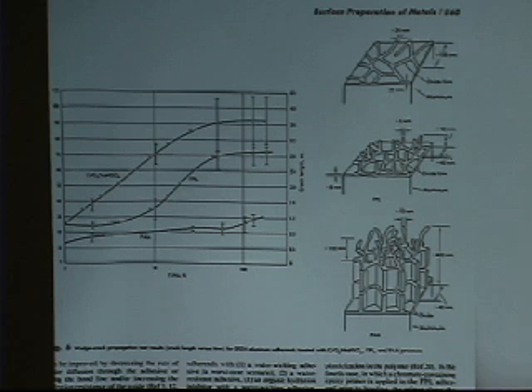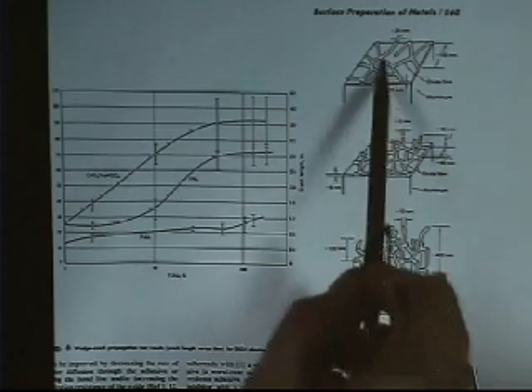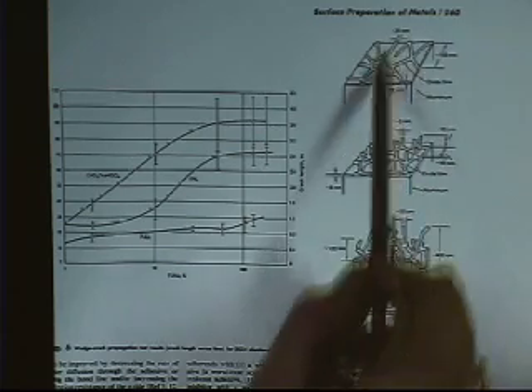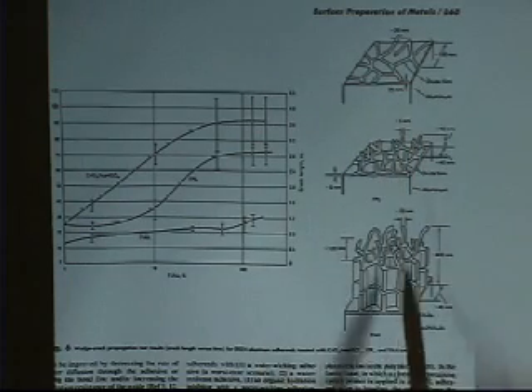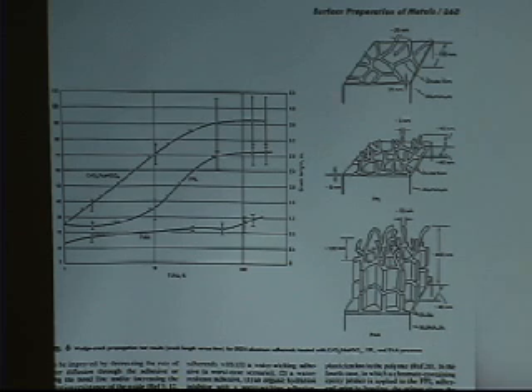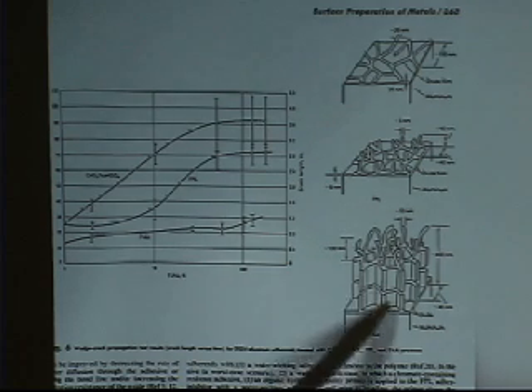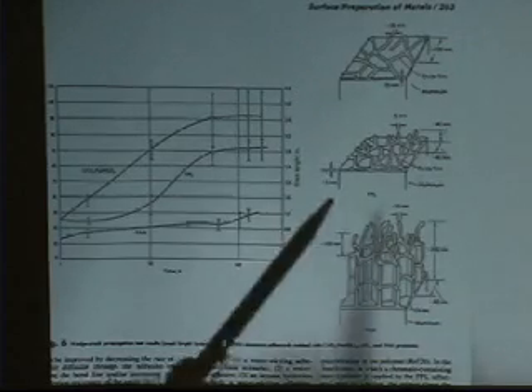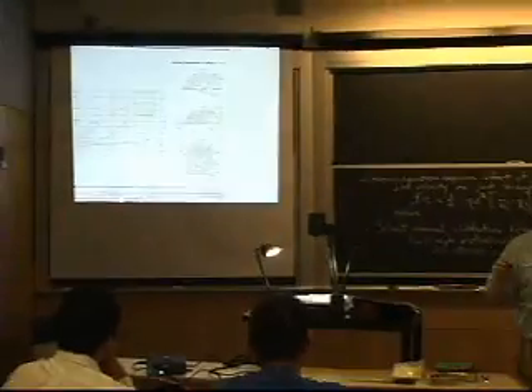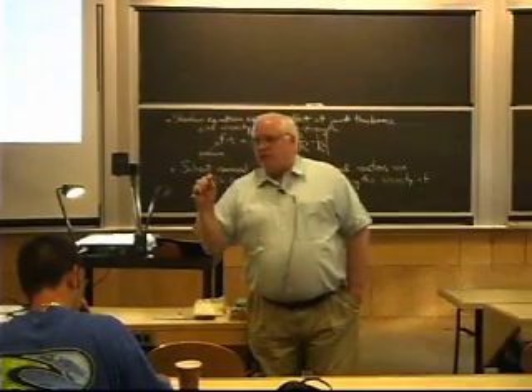By passing the electric current through it with the right type of solution, and this happens to be a chromic acid anodize on aluminum, you will grow an oxide film on the aluminum, but you'll grow it in a controlled way. However, the current has to still get into the aluminum metal, and the way the oxide film grows is essentially a very porous mass of oxide that starts growing out at about 20 nanometers, 200 angstrom wide channels, and it grows up, the little fingers grow up, and it forms kind of honeycomb type cells. They're not uniform honeycombs, but you can think of it as honeycomb type cells of aluminum oxide growing up. And depending on how you do it, you can get thicknesses that are like 3 or 4 thousandths of an inch thick.